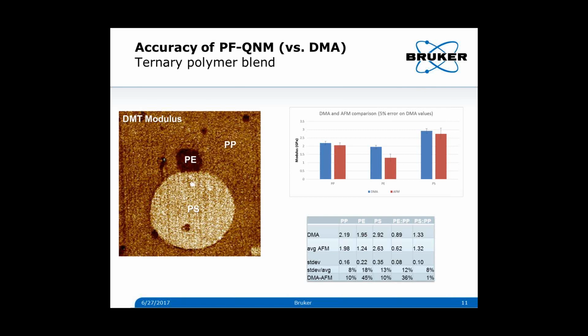Basically, comparing the DMT modulus map from QNM at 2 kilohertz to DMA also at 2 kilohertz. Looking at this ternary polymer blend, which is the same one Dalia looked at with polystyrene, polypropylene, and polyethylene. Except for the polyethylene, our results agree within the error predicted in the previous plot.